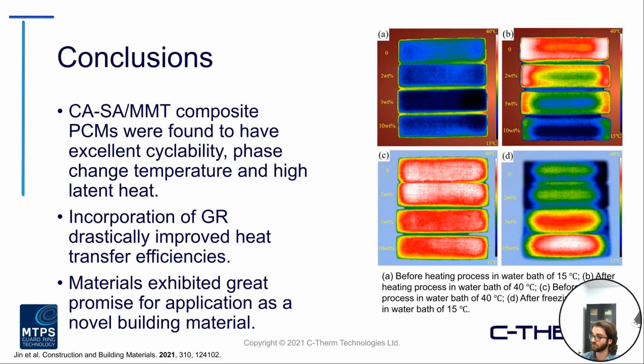The images on the right were them taking that PCM with the highest graphene weight loading and adding it at different weight concentrations inside of a brick and a mortar, and then doing some thermal imaging studies. Again, what they were able to find, based on the higher latent heat capability of the PCM, is that it really reduced the heat loss occurring on heating and subsequently on cooling inside of that building brick sample.